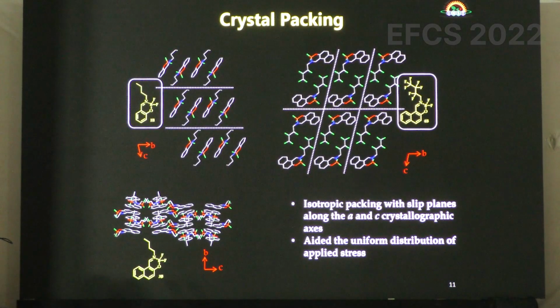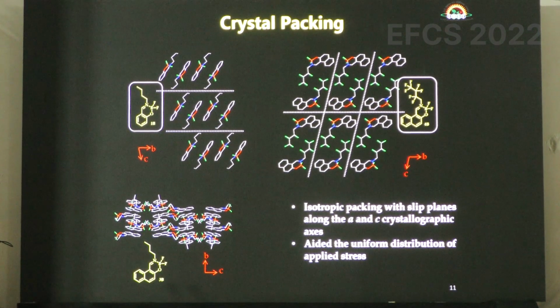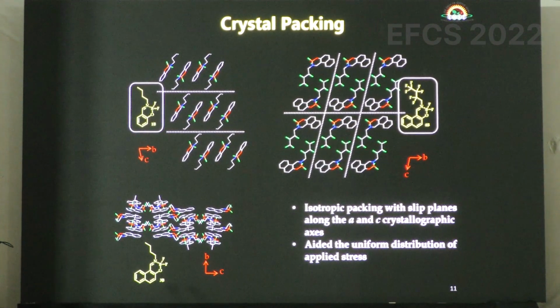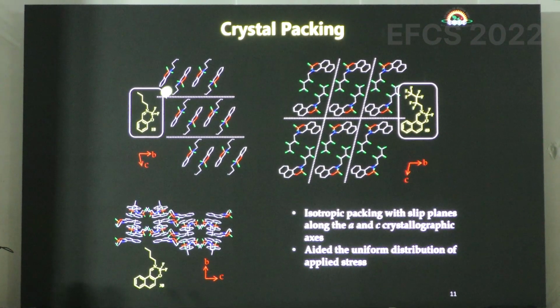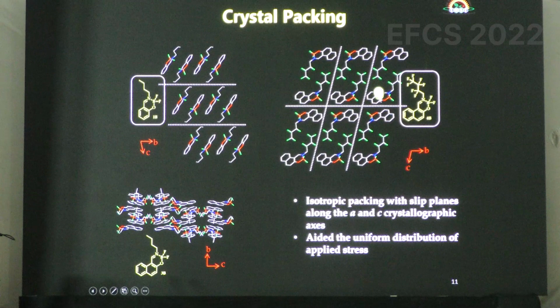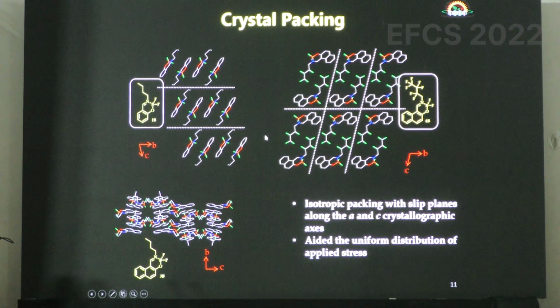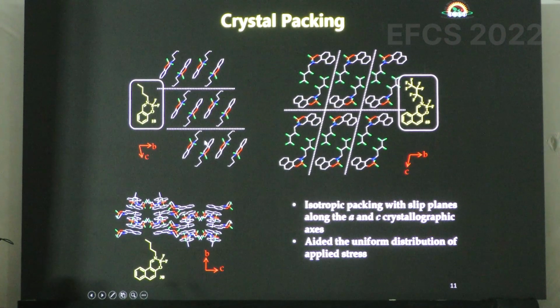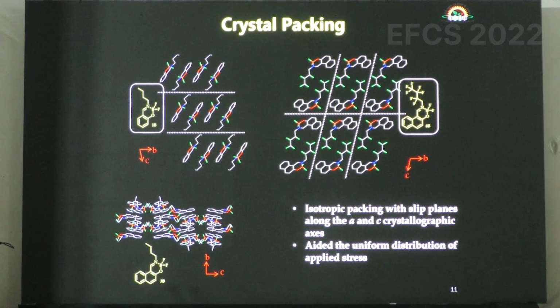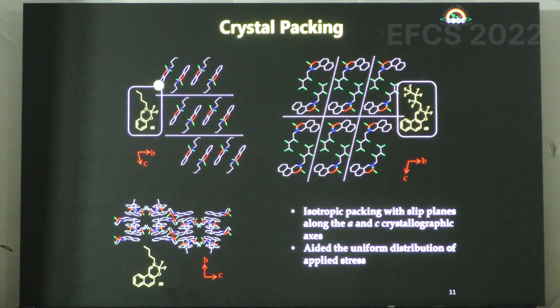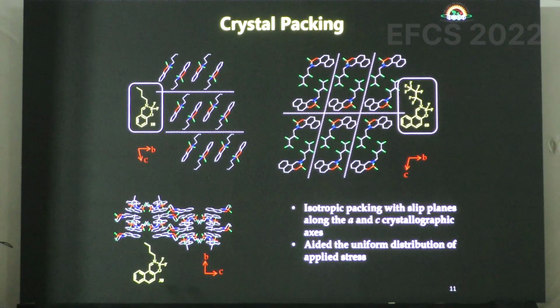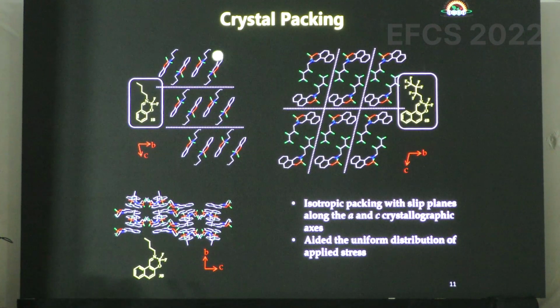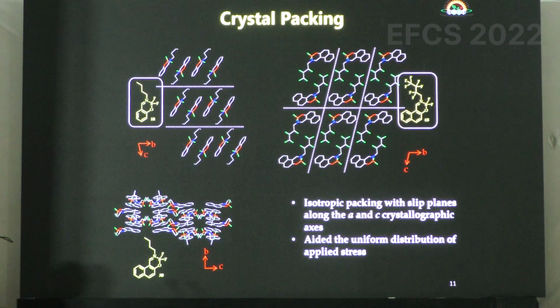So what is the reason for this? Again, we looked at the crystal packing of these compounds, and this is the crystal packing for this compound. This showed plastic flexibility, and this showed size dependent flexibility. In both the cases, there are these planes which are running in this compound. This is one molecule of this compound, and this is another molecule. They are arranged in a head to tail fashion, and this is one layer of arrangement. And between these layers, we have a slip plane running through that. We call it slip planes. And that is true in the case of the other compound also. Again, two molecules assembled, and there are these layers of dimers, and between these layers you have these planes in both directions in this case.